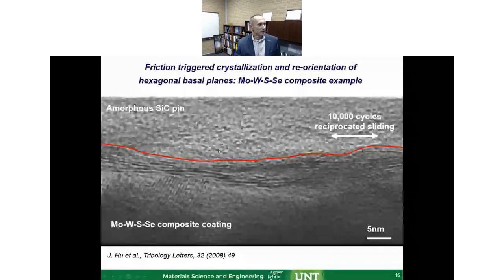So we're looking here at the cross-section of the wear track in reciprocating sliding for the moly tungsten sulfur selenide coating up to 10,000 sliding cycles, and the friction was stopped. And then we're looking right on the counter here through transmission electron microscopy. You can go to the brilliant work by Jingjian Hu in Tribology Letters, who was explaining how, using the FIB and TEM, he was able to do that.